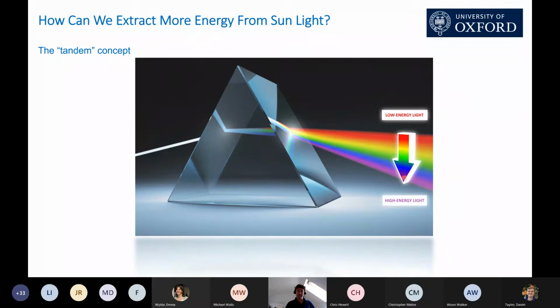And in fact, instead of just absorbing the sunlight in a single material, silicon absorbs the visible light and some of the infrared. And if you absorb it in a single material, there's a fundamental limit to how efficient that solar converter can be. I won't go into the details. You'll either know it or you don't know it at the moment, but basically about 70% of the energy has to be thrown away primarily as heat or as simply non-absorbed photons in that conversion process. So a perfect solar cell using a single material can only be 30% efficiency at absolute best. And that puts a fundamental limit to how efficient silicon can get on its own.